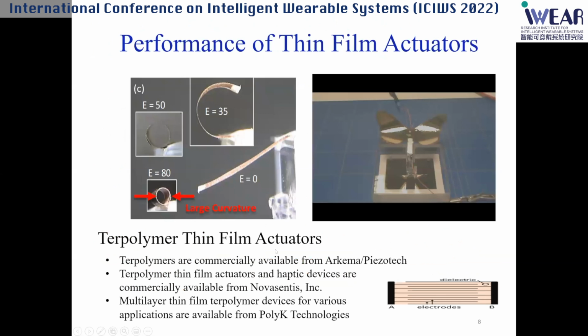So here are two examples. This is a thin film bimorph, about 2 centimeters long, about 40 microns thick. You can see when you apply electric field, you can generate shape change from this flat shape into very small curved ones.